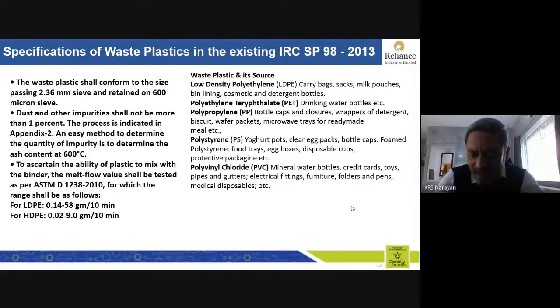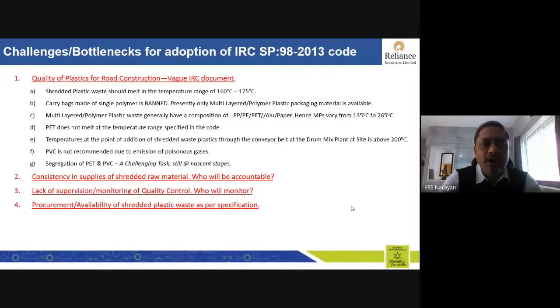And I could see that in a lot of places plastic roads had failed, basically because of the poor quality of raw material which had gone into it, because this code was very vague. Challenges, bottlenecks for adoption of that code: you have the code which mentions the shredded waste plastic should melt at the temperature of 160 to 175 degrees Celsius. Carry bags, again, are banned now. Presently, only multi-layered polymer plastic material is available.